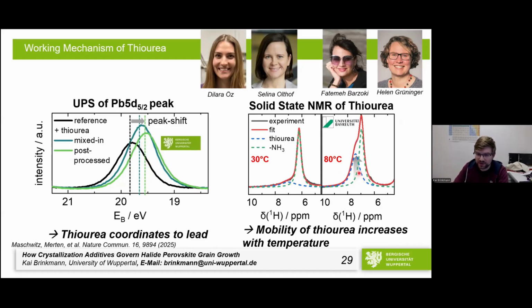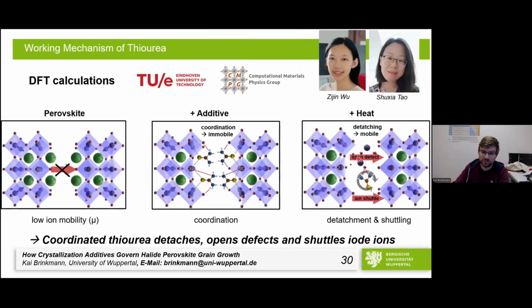And then if you increase the temperature in solid state NMR, you can see that the thiourea actually regains mobility. So if you then increase the temperature, the thiourea can move. And then we went over to Zijin Wu and Shuxia Tao, figuring out what the heck this thiourea could do there. And it turns out that the thiourea is actually an ion shuttle. So it seems to be that the thiourea is able to coordinate to both the lead and the iodine, shuffle the iodine over there, and thereby increase the ion mobility in our material. So an increase of ion mobility at higher temperatures gives us big grains.